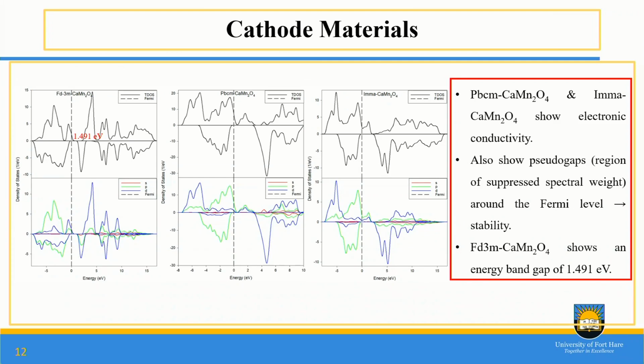So we went on to determine the electronic conductivity. This is determined by measuring the size of the band gap. We know that materials with a band gap are insulators. The materials without band gaps are either semiconductors or conductors. So when we look at the FD3M, we see that it has a band gap, so it may not be a good conductor. Then we look at the PBCM and also the IMMA. We see that they do not have a band gap along the Fermi level. That means that electrons are allowed to jump from the valence band to the conduction band, which attributes to good conductivity. So that's what we have seen with these materials.